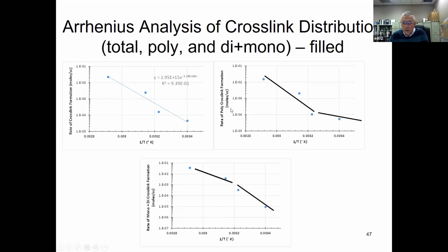We plot total crosslink density. But if you look at the polysulfidic and the mono plus disulfidic, we see evidence for mechanism change around 50 degrees centigrade. The rate of formation of polysulfidic is following nonlinear, non-Arrhenius behavior, and the formation of monosulfidic is following non-Arrhenius behavior.